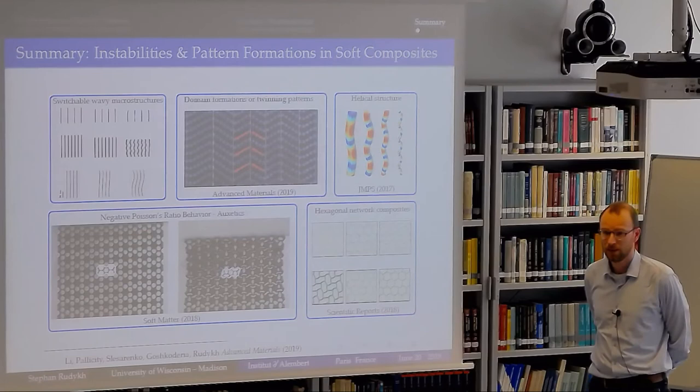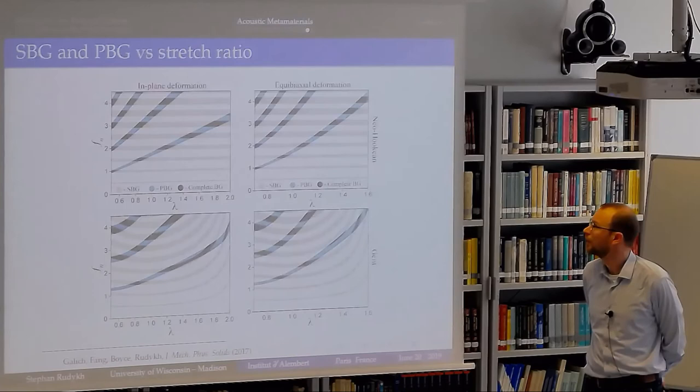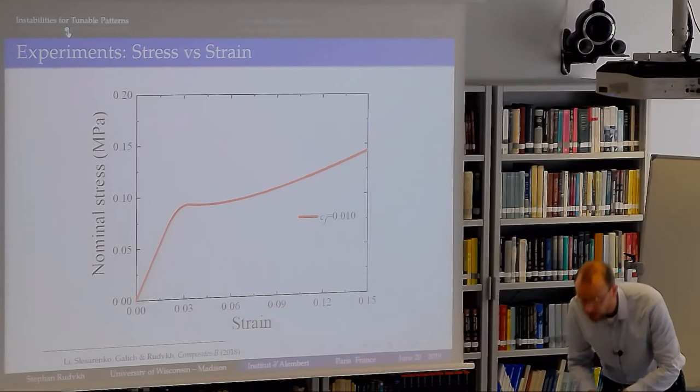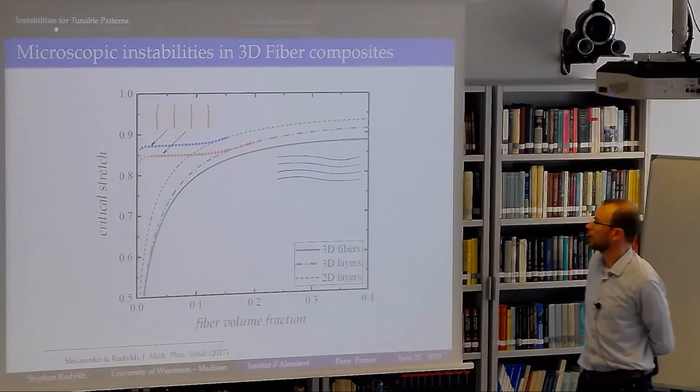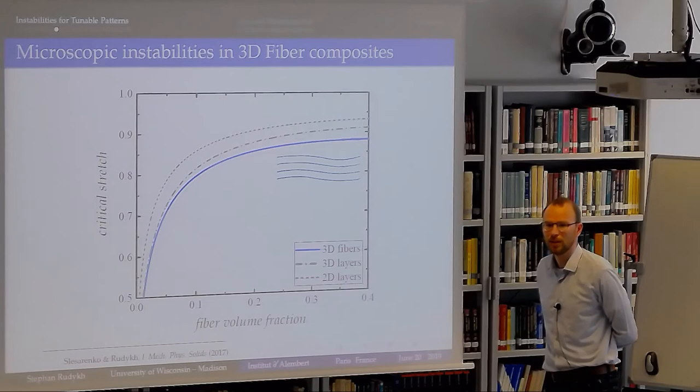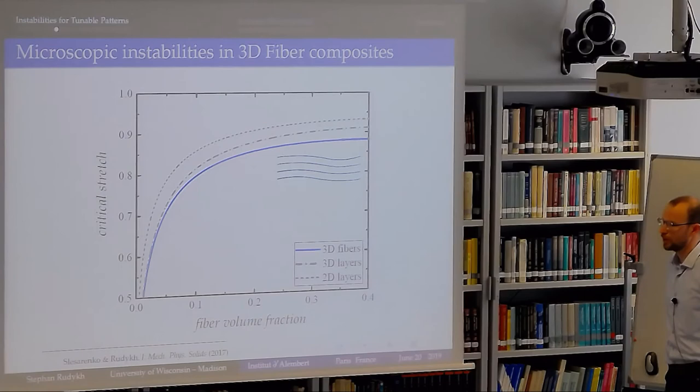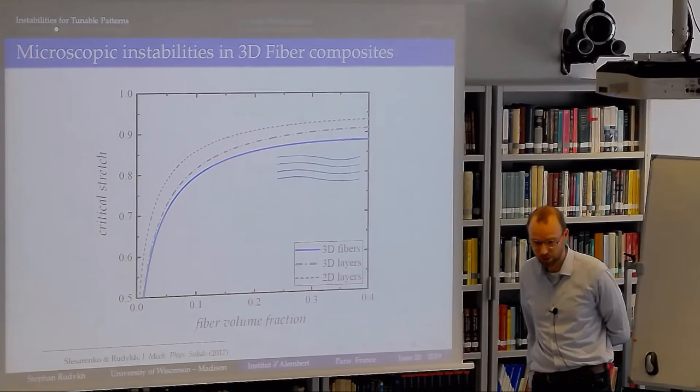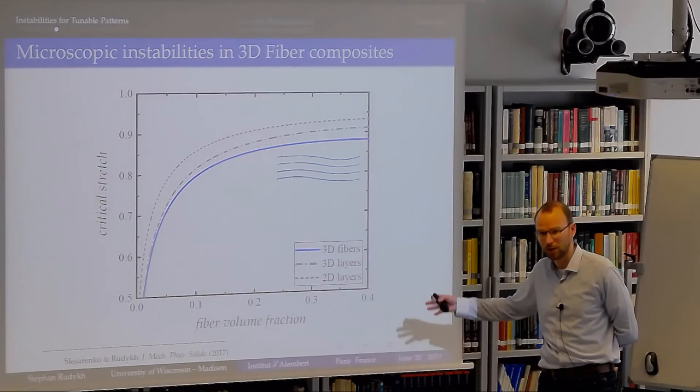Thank you. In the first part of your talk, you discussed strain rate effects in this composite material. I was wondering what kind of constitutive viscoelastic model you have used. It was a really very simple one that we adopted, what is called quasi-linear viscoelasticity. You have a Prony series, so you still have large deformation, so you incorporate hyperelasticity, and then you have on top of that some relaxation function that accounts for hysteresis, all these exponents that you can integrate.